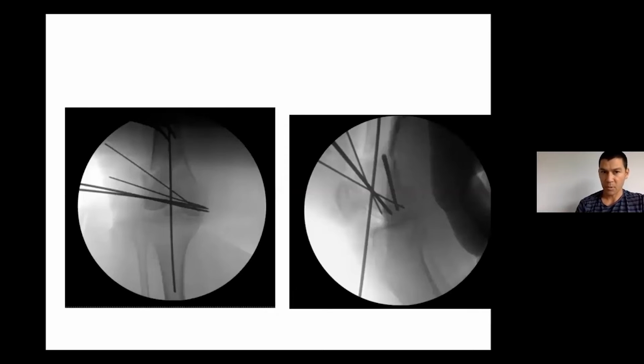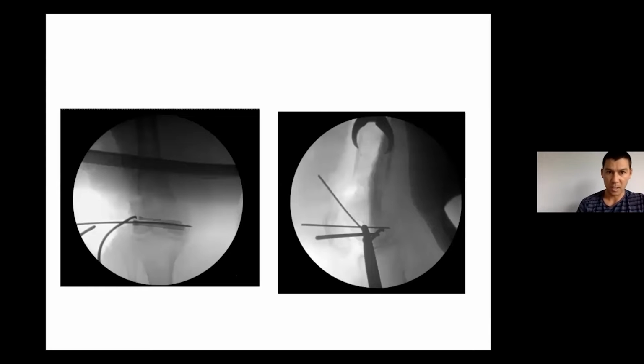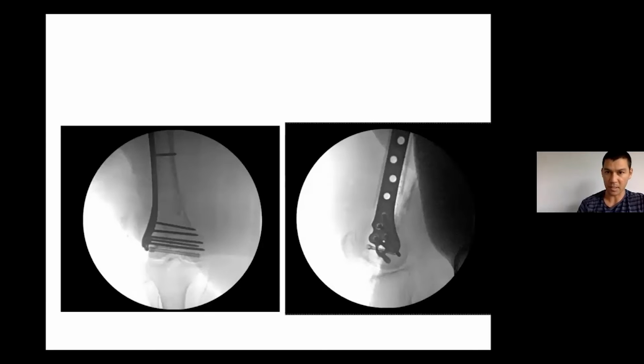So I put her joint back together, and I put some wires through the notch because her bone was so bad that nothing was holding except for that notch bone. But we were able to get an anatomic reduction of the joint, which was a fairly simple thing. And I put a guide wire up through a very small 5 mm incision for the IlluminOss device. And that's the IlluminOss device deployed within the canal, filling it and giving it a lot of extra, well, not bone stock, but a lot of extra strength for placing a percutaneous laterally based plate.